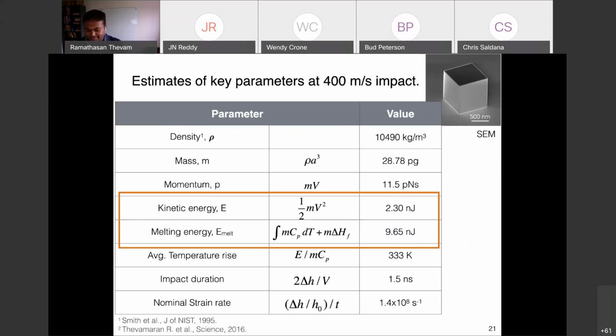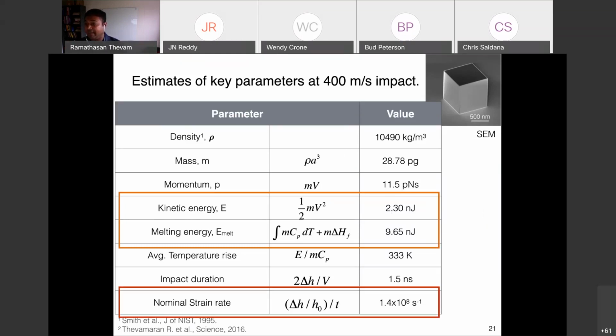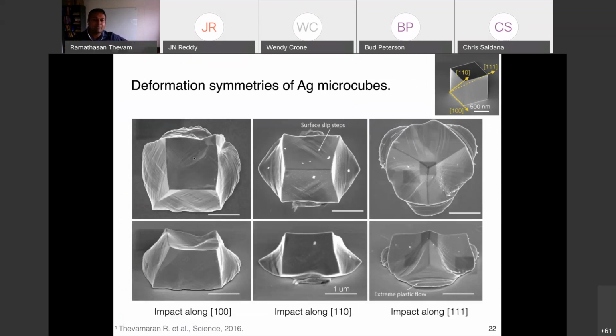So anything I will show is a solid state process. You don't see melting. And the strain rates are very high, all the way up to 10 to the power 8 second minus 1. So this is very high strain rate deformation. If you take this cube and impact it, this is a face impact, an edge impact, and a corner impact of the cube. These are the tilted side views, all taken in a scanning electron microscope.